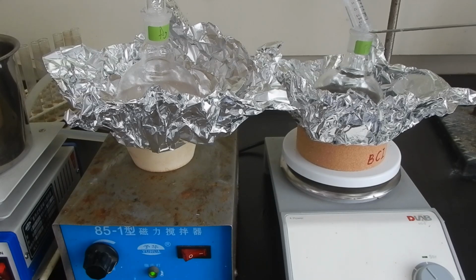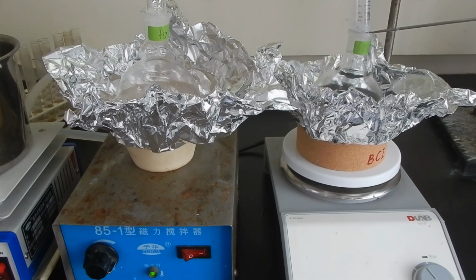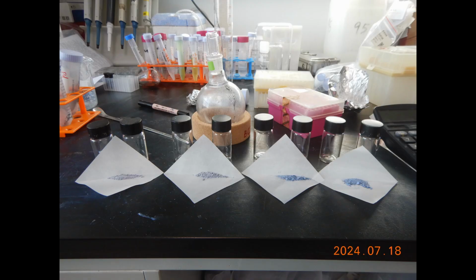The catalyst containing palladium is prepared exactly the same way, except that palladium chloride is used in place of silver nitrate. And here we have the 2 catalysts laying side by side, silver on left and palladium on right, ready for testing. You can see that DMSN-Pd is distinctively bluish compared to DMSN-Ag, which is more of a pale lilac color. I assume this is due to size difference of metal nanoparticles.